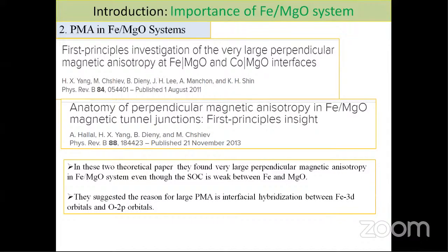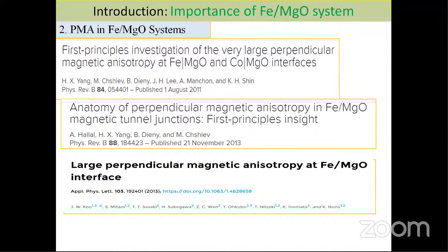They suggested that the large perpendicular magnetic anisotropy is because of the hybridization between Fe 3d orbital and O 2p orbital. This was experimentally observed in the Fe/MgO system. Another important property in Fe/MgO trilayer is interlayer coupling, where a very thin film of MgO is sandwiched between two magnetic layers, and these two ferromagnetic layers are coupled by the thin MgO layer. And the most interesting property of the Fe/MgO system is unusual magnetization reversal and in-plane magnetic anisotropy.